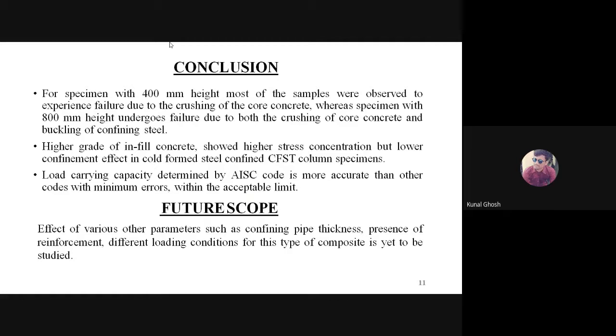Conclusion: for the specimen with 400 millimeter height, it was observed that failure was due to core concrete crushing, not local buckling of steel confinement. But for the 800 millimeter column, it was observed that the core concrete failed due to crushing, and the confining steel also failed due to local buckling.